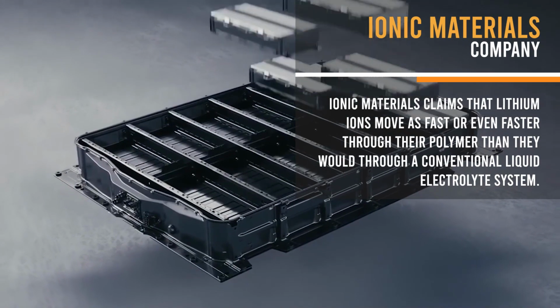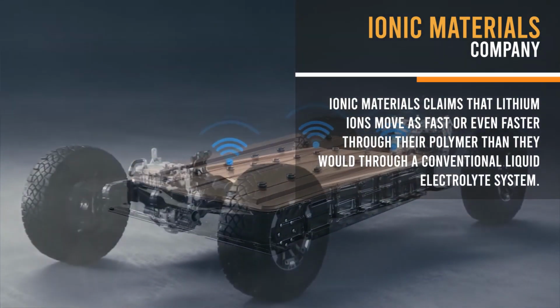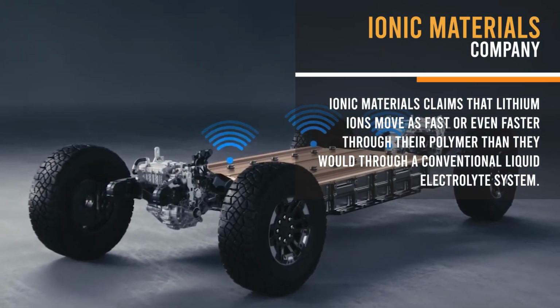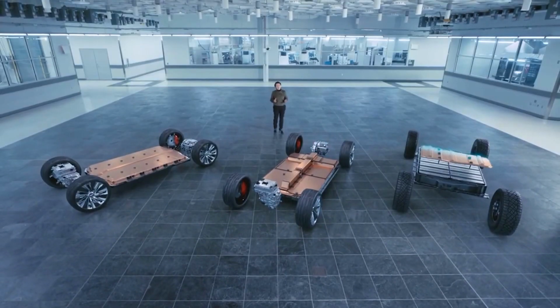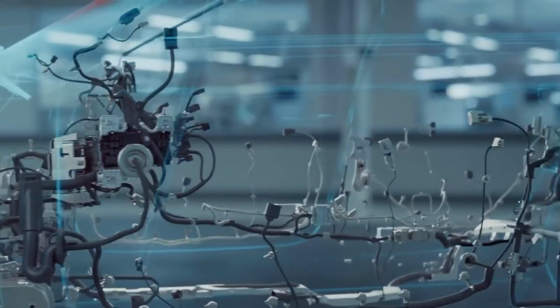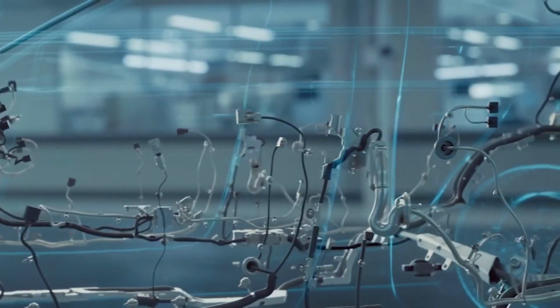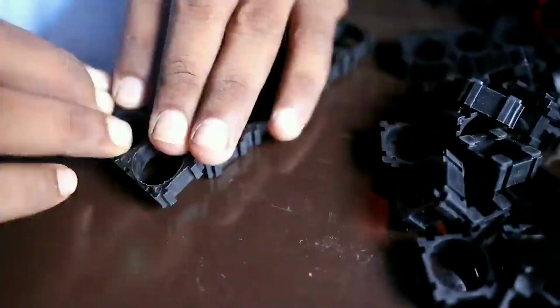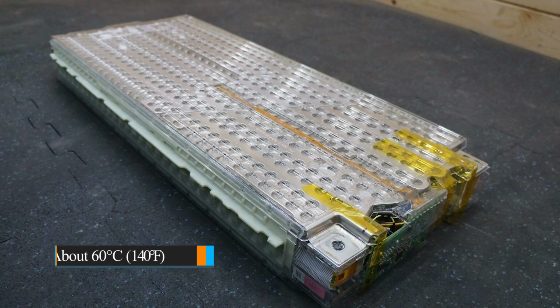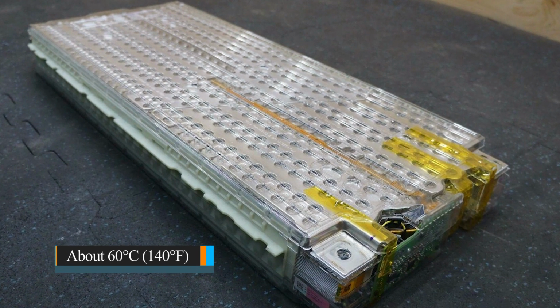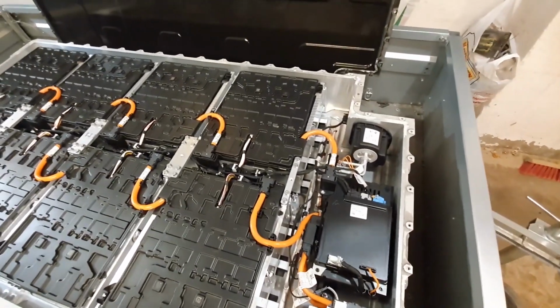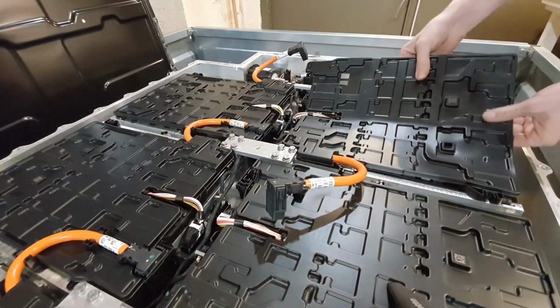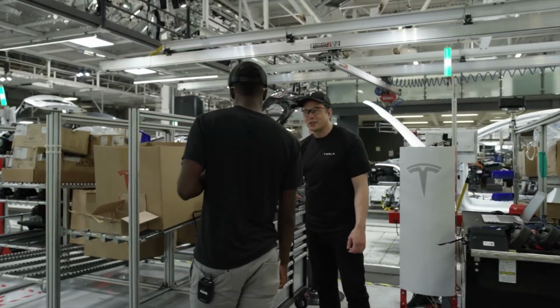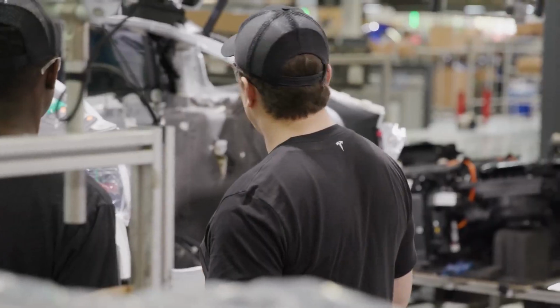Ionic Materials claims that lithium ions move as fast or even faster through their polymer than they would through the conventional liquid electrolyte system. This helps demonstrate the stability of the company's polymer material. Second, the polymer works at 5 volts and can be made simply and cheaply. Third, while most materials in solid-state research operate at about 60 degrees Celsius or 140 degrees Fahrenheit, the firm's material works at room temperature. It is evident that solid-state batteries are the next big thing. But until it picks up, Tesla is still competitively ahead thanks to its early adoption of the years of research in lithium-ion battery making for EVs.